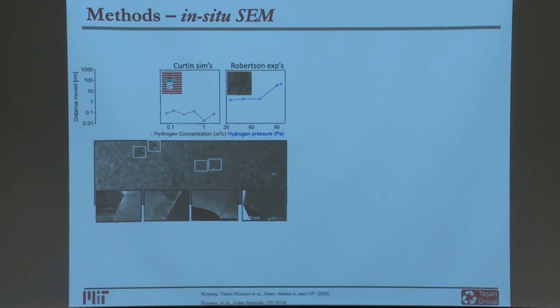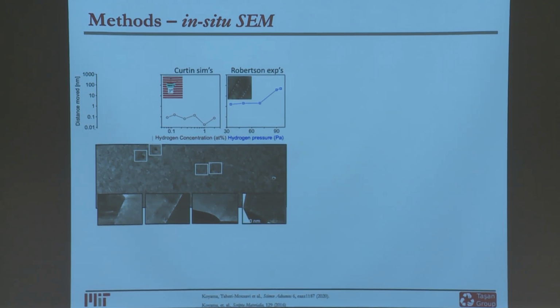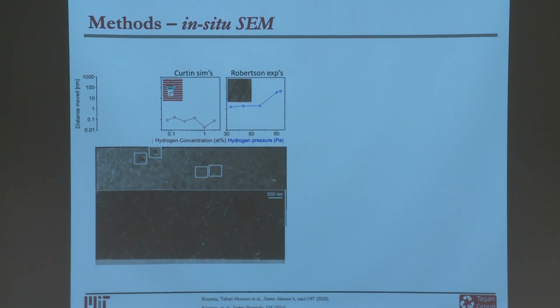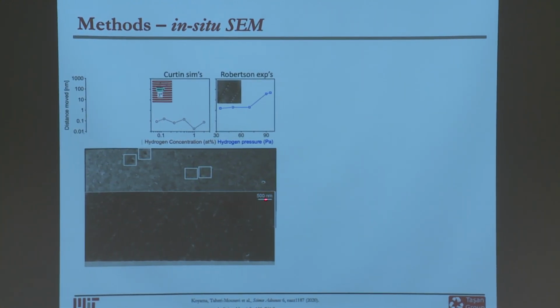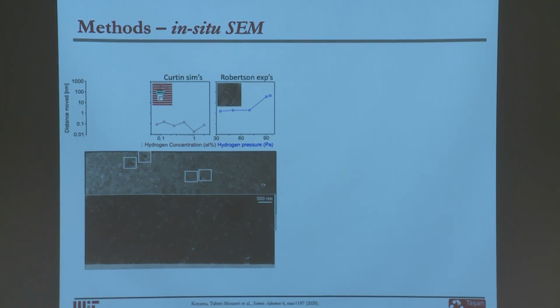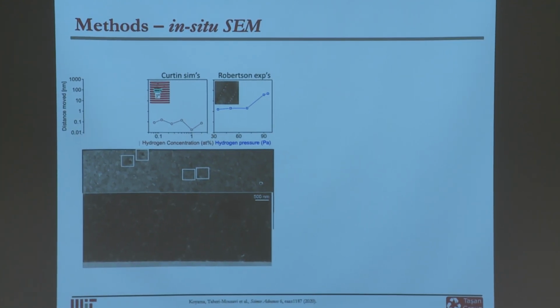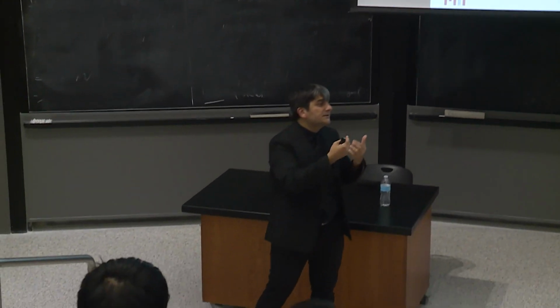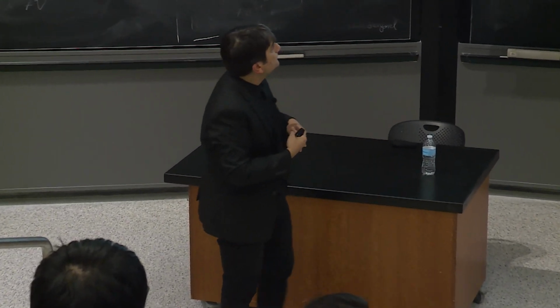Now, remember what I was saying before. We can look at very large regions, but we still have the right resolution to see the details. So in this case, in the SEM, you can do ECCI, electron channeling contrast imaging. Now, for instance, pay attention here to the micron bar. This is half a micron, and we are looking at a region that's microns long, and we are looking at individual defects, dislocations, dancing around, as we charge hydrogen to the sample from the bottom.